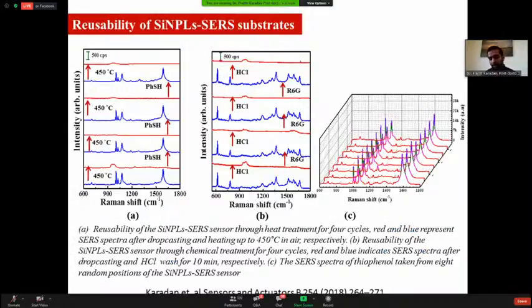In the previous slides, I already mentioned that reusability and reproducibility of the sensor is a very important thing. We tried reusing the substrate by heating it after recording the spectra using some analyte. We heated it above 450 degrees Celsius and then recorded the spectra. It showed nothing, no spectra over there. Then again we drop-casted the molecule and recorded the spectra. We repeated this some 8-9 times to confirm the reproducibility and reusability of the sensor.